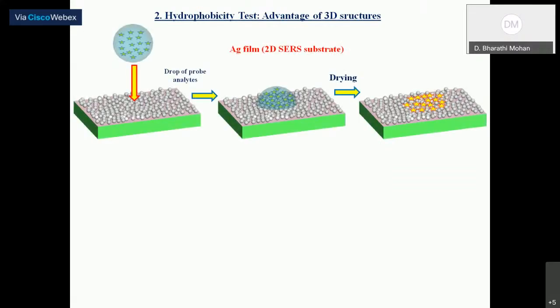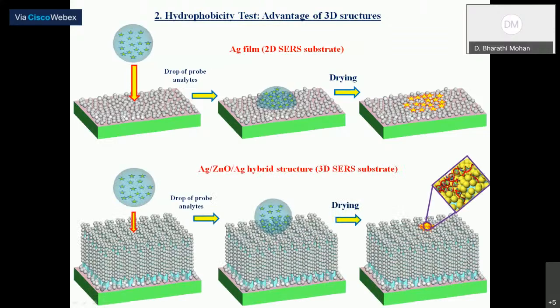Another aspect is called hydrophobicity. The hydrophobicity is much better in the case of a 3D structure. You can see the schematic diagram. If you take a 2D substrate and drop cast analytes on top, it covers a larger area on the 2D substrate. Whereas if you take a 3D substrate and drop cast analytes, they are confined into a small area. So this is the advantage of the 3D substrate. The confinement of probe molecules will help to increase the Raman scattering of the probe molecule.